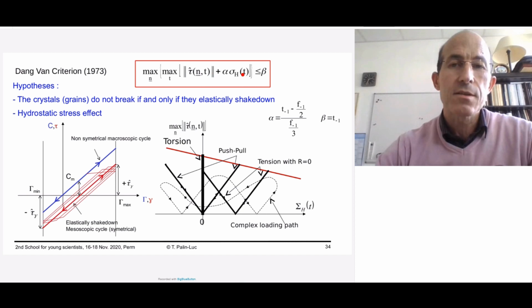So Dang Van considers a linear combination like Crossland of the hydrostatic stress at the mesoscopic scale and the shear stress vector amplitude on the material plane. So this criterion, in fact, predicts that there is an elastic shakedown of the shear versus the shear strain. So you can see here at the macroscopic scale, there is a decrease of the mean shear stress when you look at the grain scale. This is due to the assumption of the criterion.